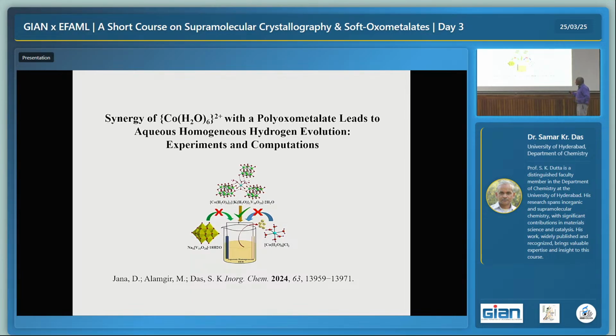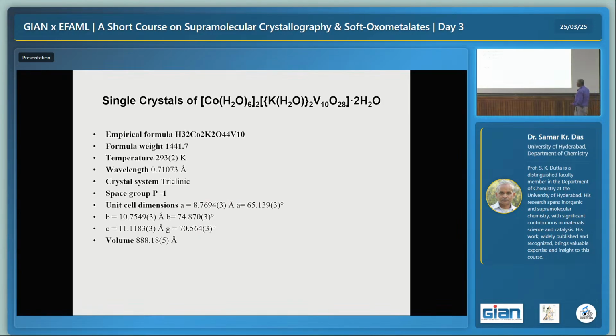So the synergy between cobalt and the cluster by hydrogen bonding is very important. What I mean? Again, let me tell you, maybe you missed it. I am talking about this single crystal structure. If you see the structure, you have the cobalt aqua compound, which is like that. You have the decavanadate cluster. That means if you mix them, they should give water oxidation, but they don't. Only the compound of which we got the single crystal, when we dissolve that, gives water oxidation. That means the crystal structure is maintained in solution, and that gives the water oxidation.